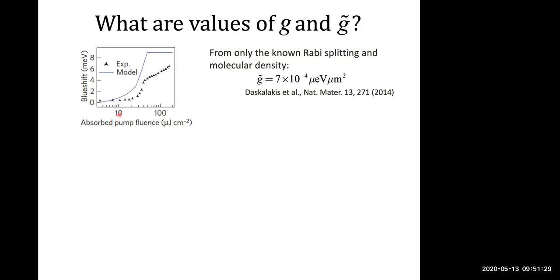And if you just take this number and try to reproduce the blue shift as a function of pump power without any fit parameters, and this is just taking the molecular density, you find that qualitatively it agrees relatively well with the measured blue shift, which is given here by these triangles. Now this model only works until this point here, beyond which in these polariton condensates, the reservoir density gets clamped at the threshold value. So this is just like in a regular laser. So reservoir density gets clamped, so the blue shift due to the reservoir, which is this G tilde, no longer plays a role.